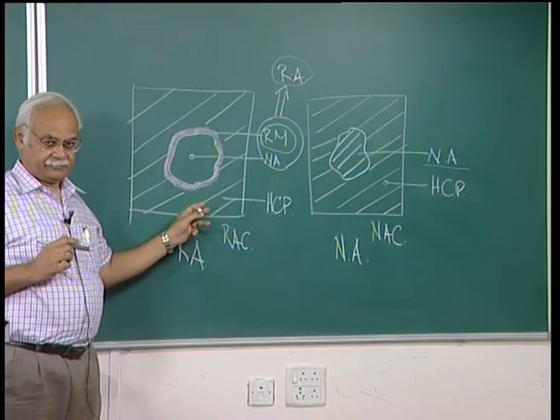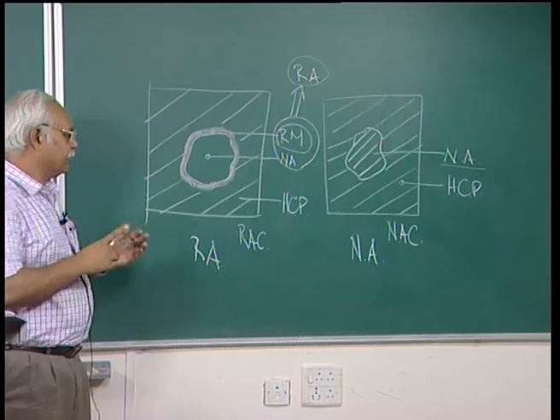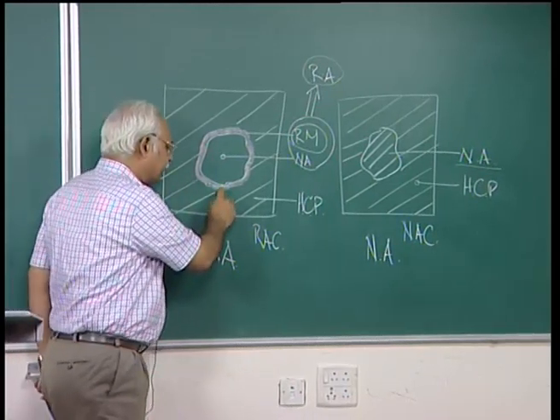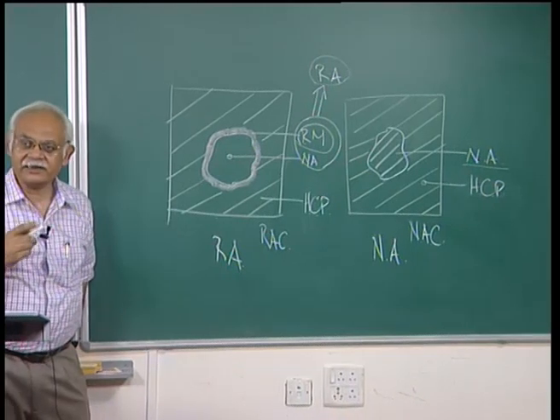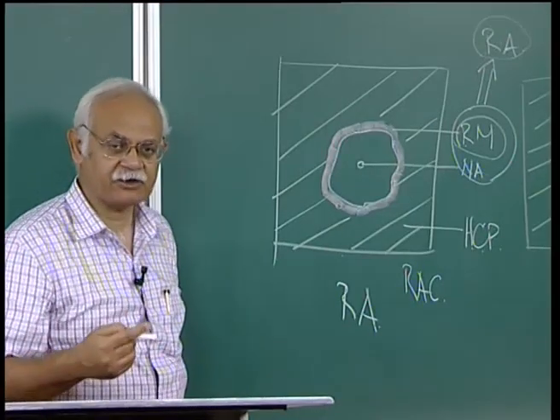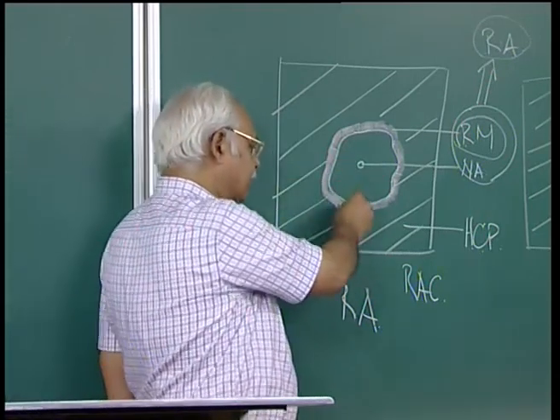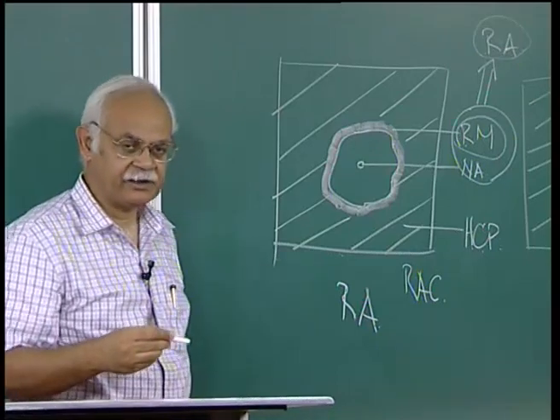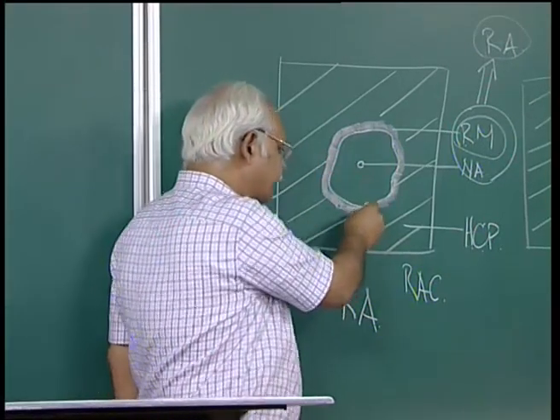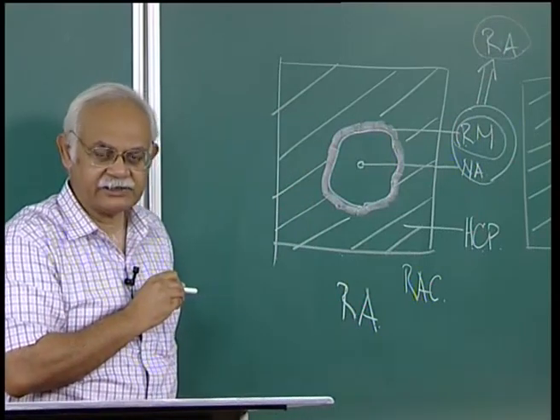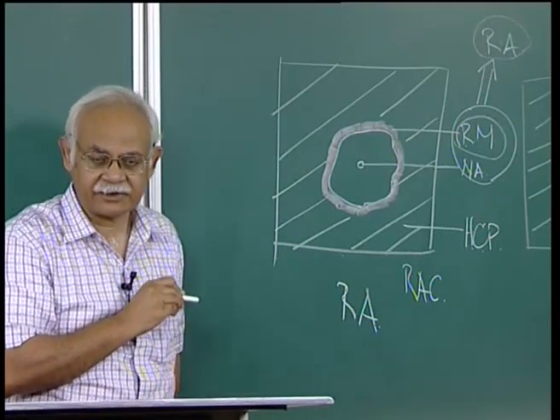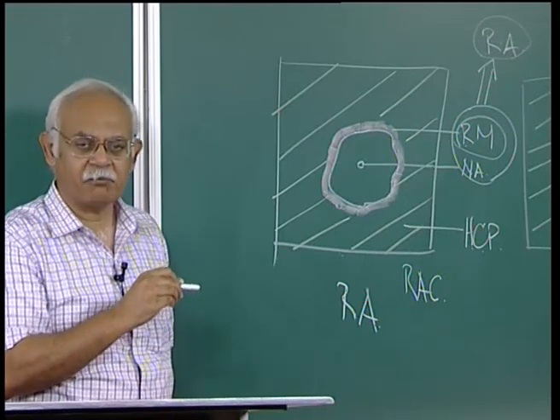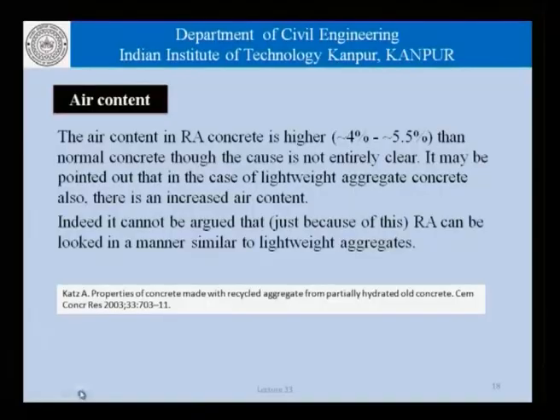We go back to this understanding of concrete. As far as workability is concerned, the effect of this residual mortar will again start to manifest itself, whether it is fresh concrete or it is hardened concrete. Because the recycled aggregate is lighter, the concrete will be lighter, and it is lighter because very likely whatever is adhering to the aggregate, especially in cases of aggregates derived from concrete wastes, is mortar and has a certain amount of porosity. As far as the air content in recycled aggregates is concerned, it has been reported that the air content tends to be slightly higher than in normal concrete, though the cause is not really clear.